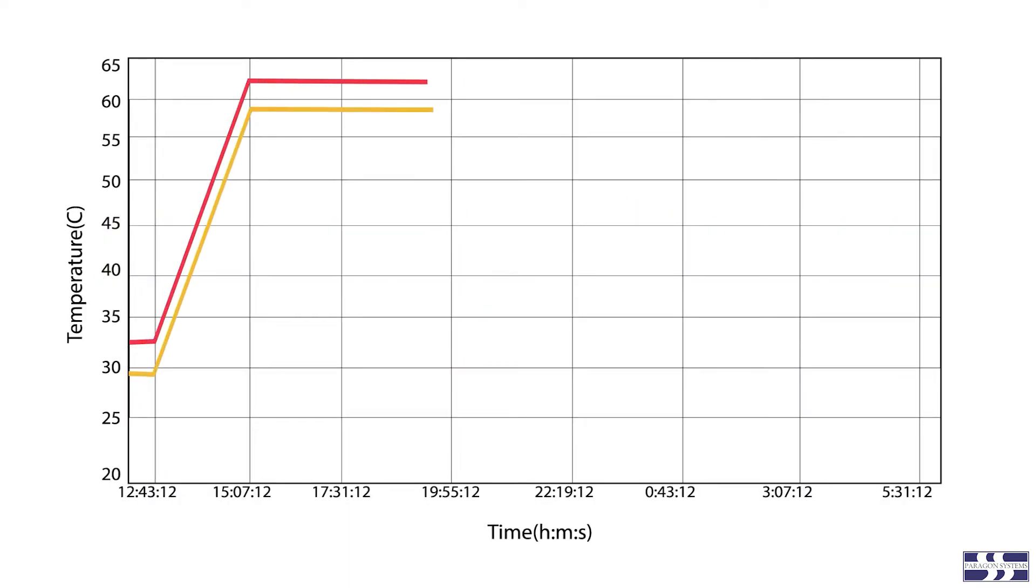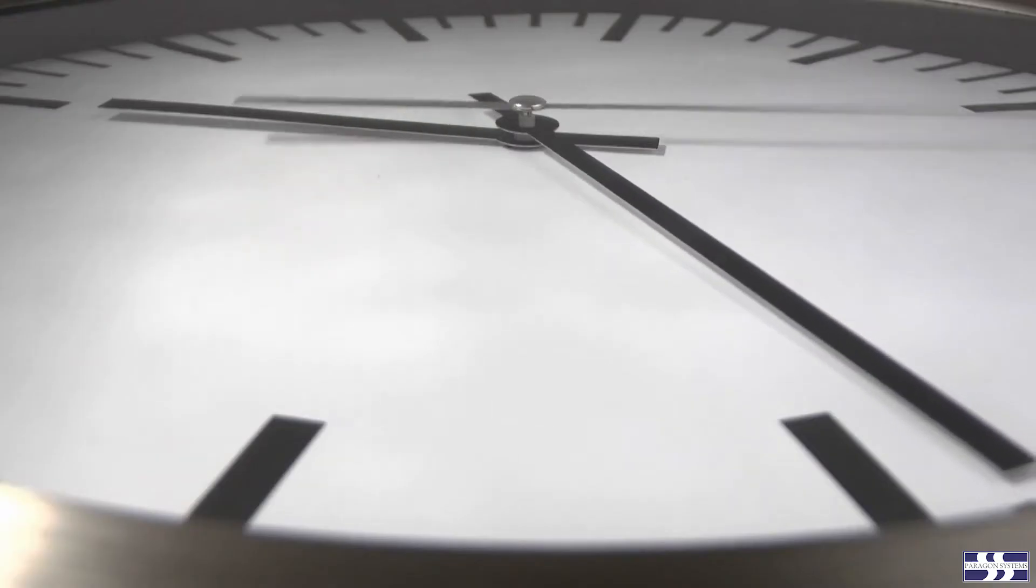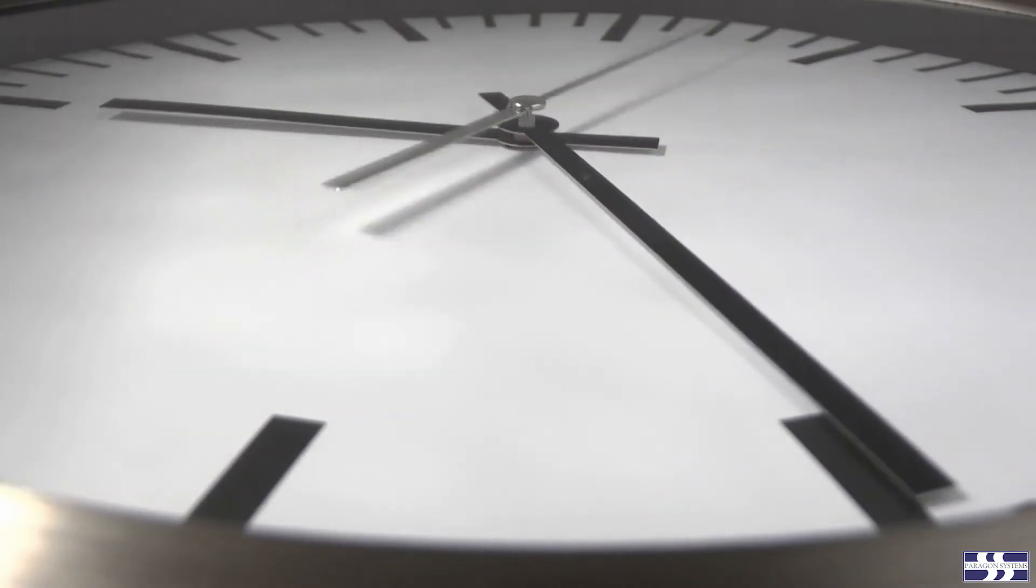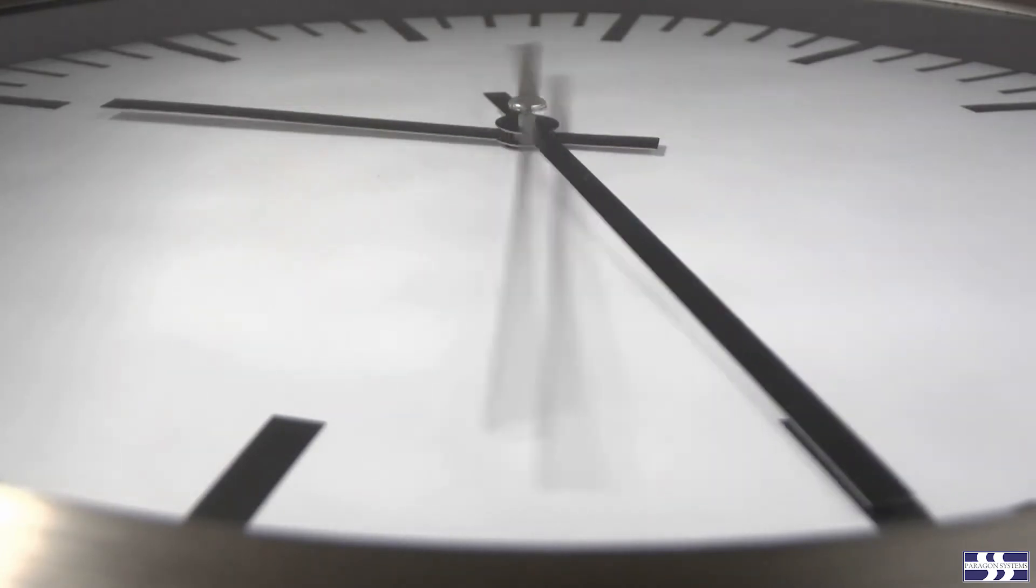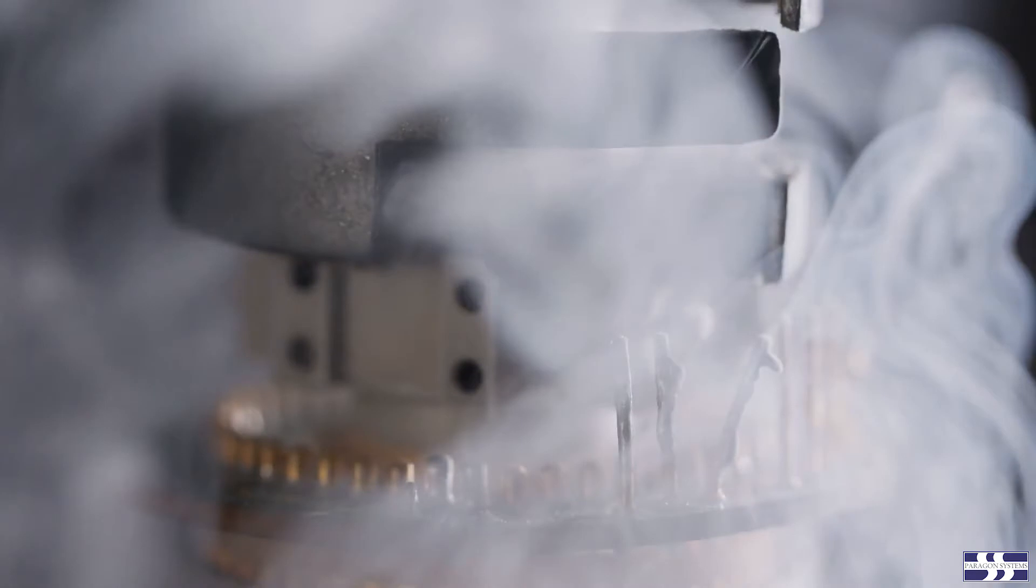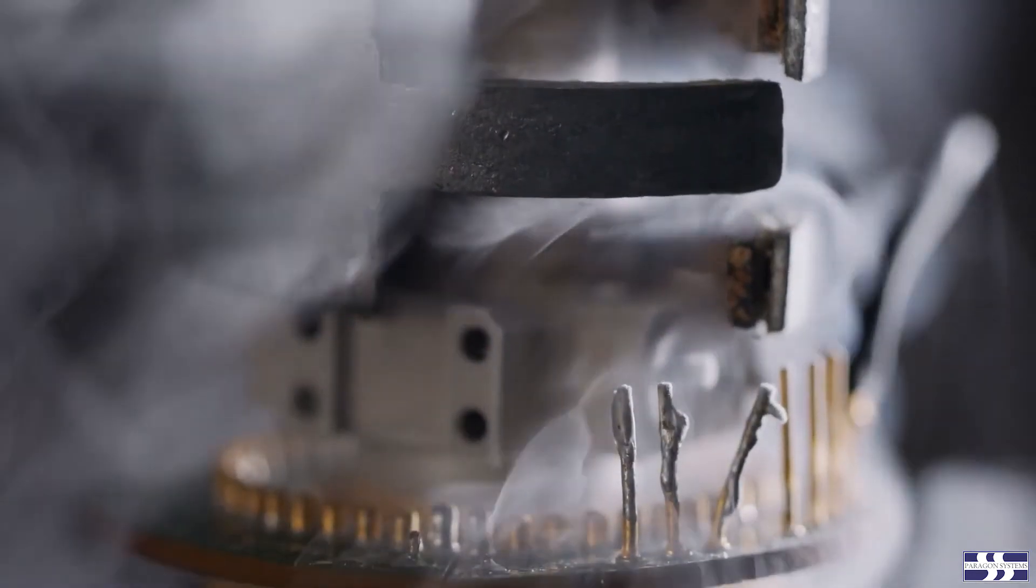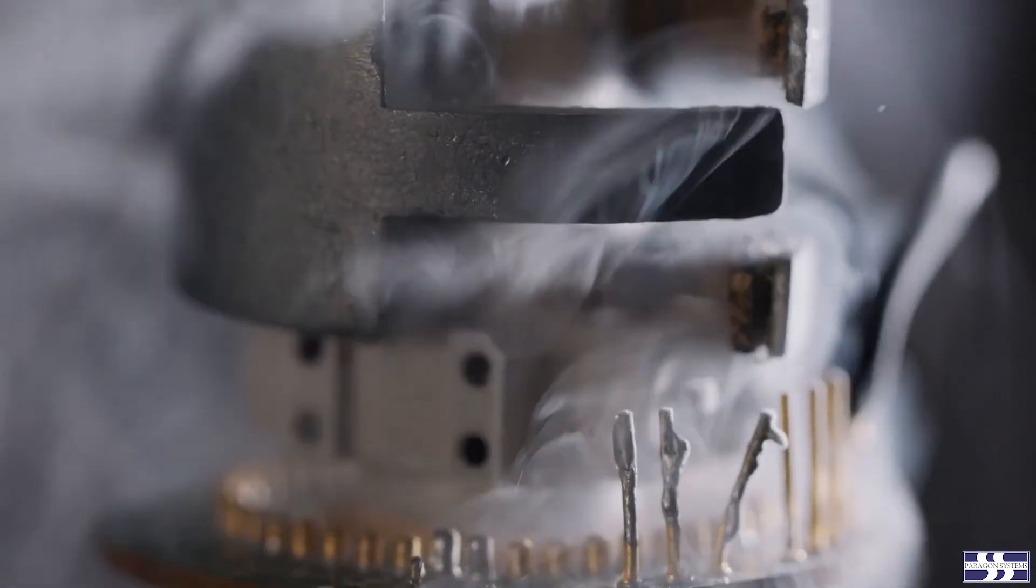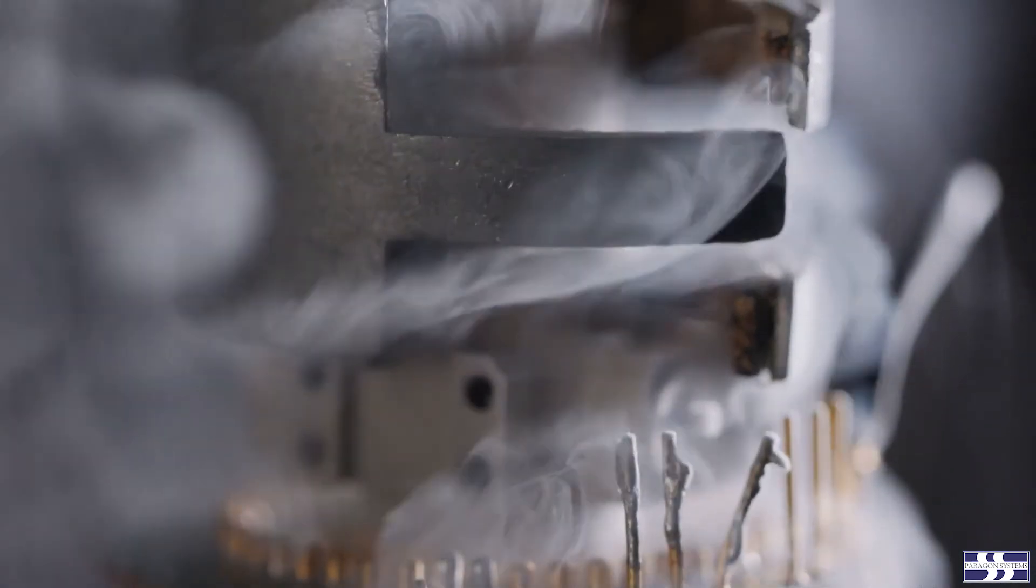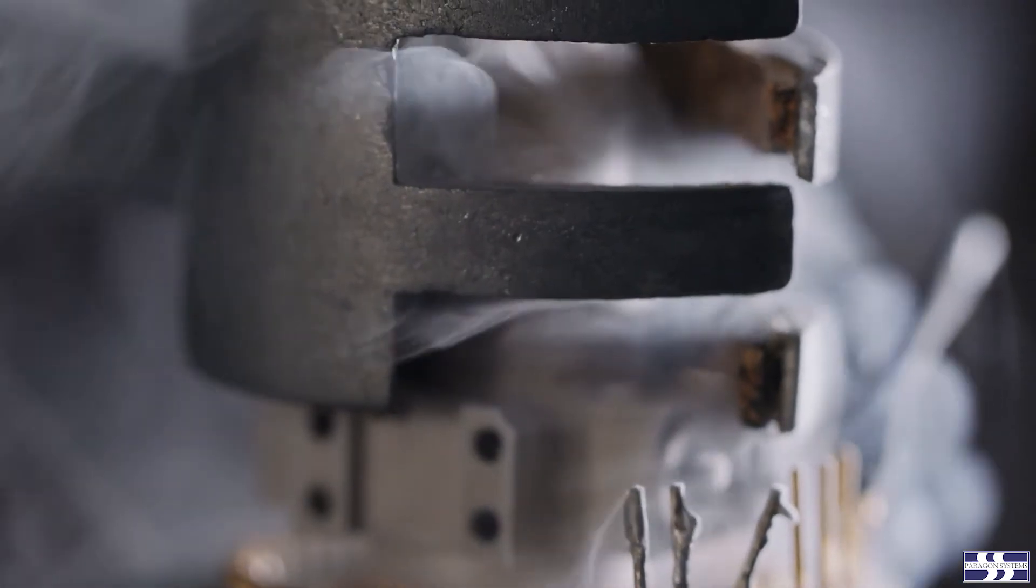At high temperatures, phenomena such as creep can become apparent. Many electronic products that may be subjected to low temperatures can be tested for low temperature wake-up after a 24-hour soak, after which the product is switched on and evaluated for proper function.